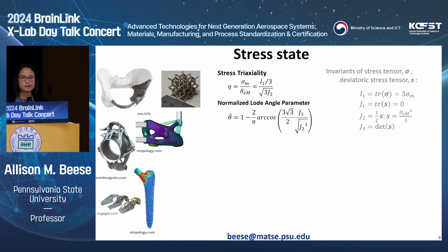in terms of when I say something about stress state. We can define our stress state by our stress triaxiality, which is just the negative pressure of our stress state. So if we have a high stress triaxiality, it's going to want to pull open pores in our sample. And then our normalized Lode angle parameter, theta bar, tells us about the second principal stress. It's a little bit convoluted, but it tells us the importance of shear, for example.